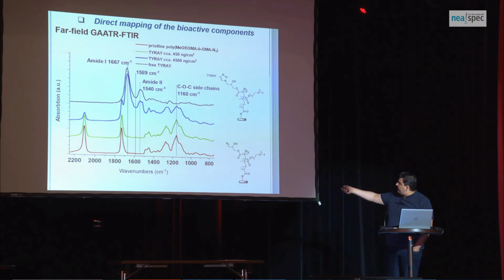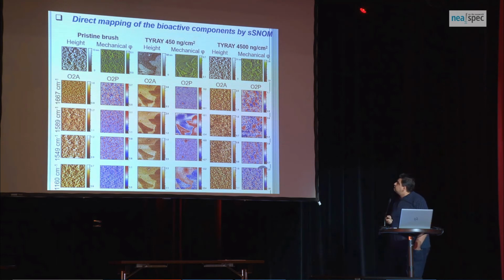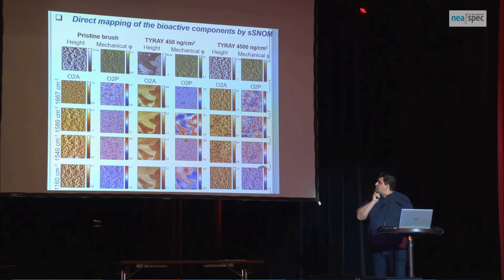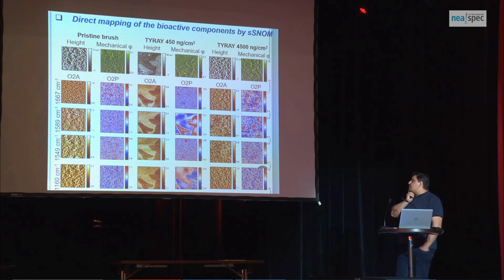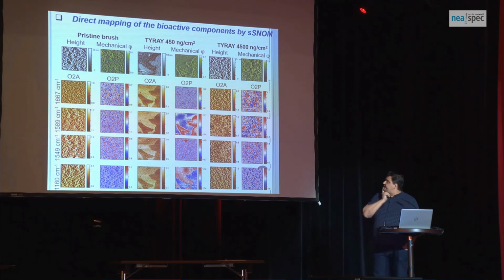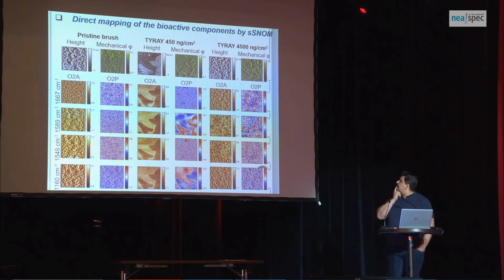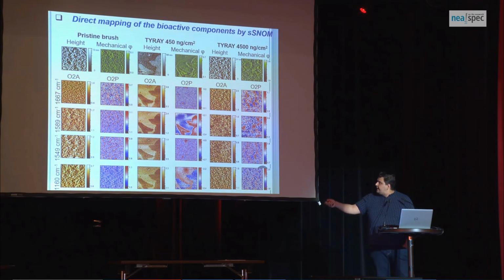This is the far field spectra of the peptide. This is the polymer brush. And these are two concentrations of the peptide over the surface, something like 450 nanograms and 10 times higher, 4,500. Let's see the sSNOM images. The pristine brush, basically no features, and different features observed over the surface of the bioactive surfaces when we have low and high concentration of the peptide. Even more interesting, this change in the contrast of the images at various vibrations, amide 2, amide 1, amide 2, and I don't know from where this one comes. This is a thing that we are still fighting with.